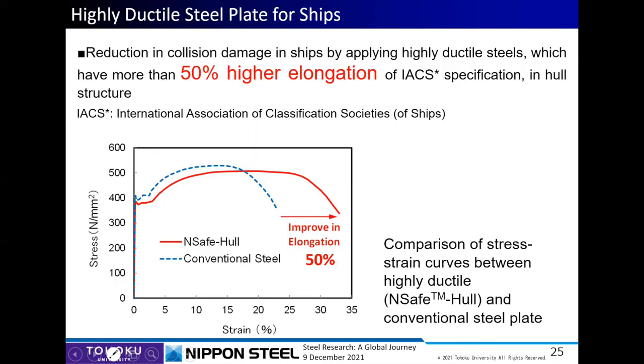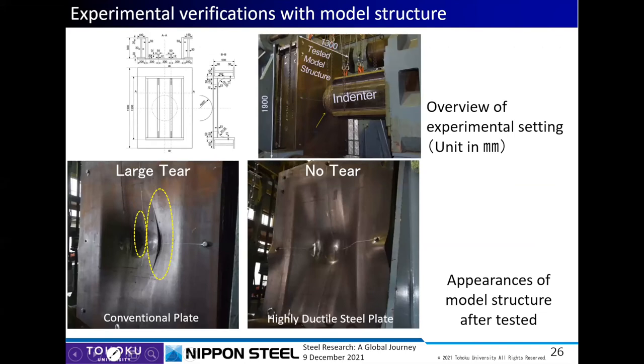This is the real stress strain curves comparison. We get higher elongation, 50% higher than conventional steel regulations. But another issue is that some people do not believe this sort of FEM calculation. Such suspicion or doubt is somehow reasonable, because in the FEM calculation we do not have any weld line.